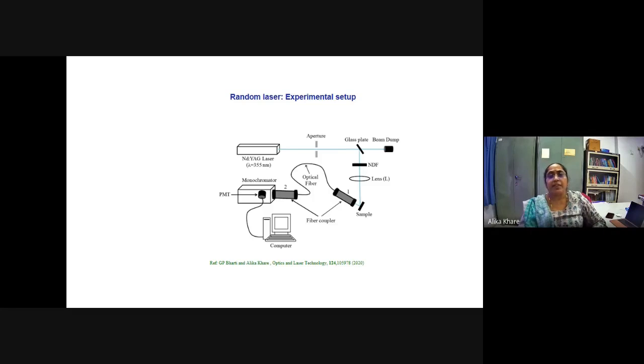Since we have a very high power laser, if we allow the whole laser to fall onto the ZnO sample, plasma will be formed, so we have to curtail the intensity. We used a glass plate so that around 10% reflection falls onto it, which we further curtailed with a neutral density filter. The radiation was then focused onto the sample, fed through an optical fiber system onto the monochromator, recorded, and fed onto the computer for data recording.